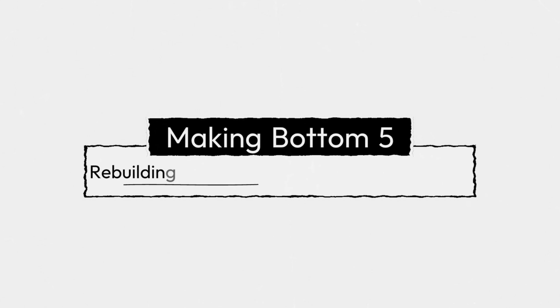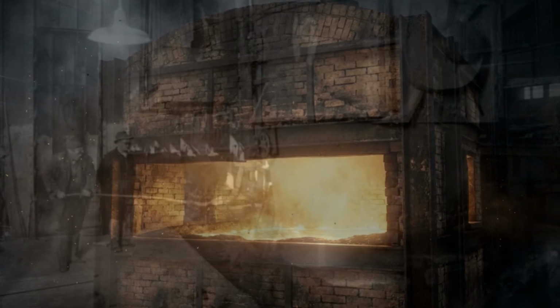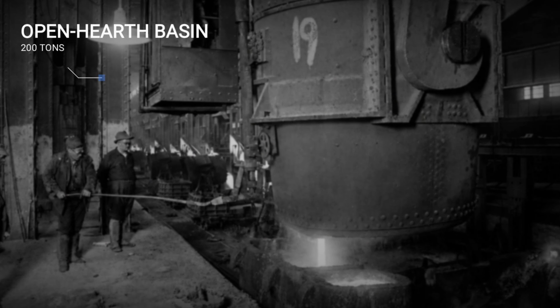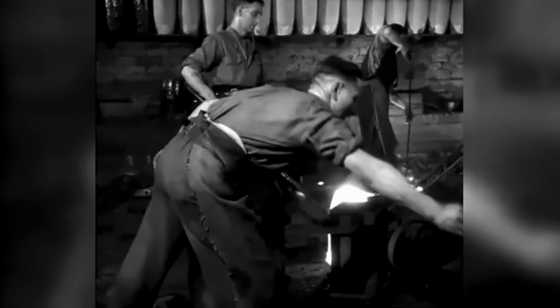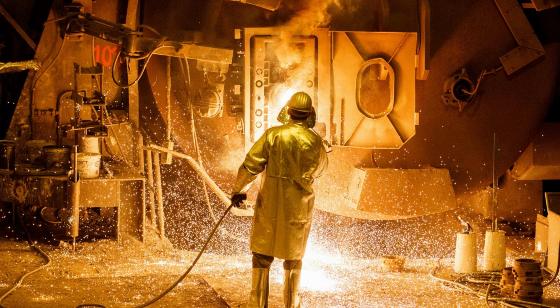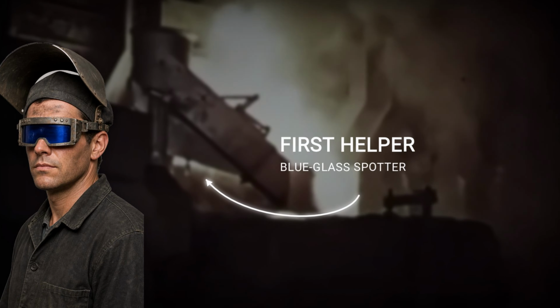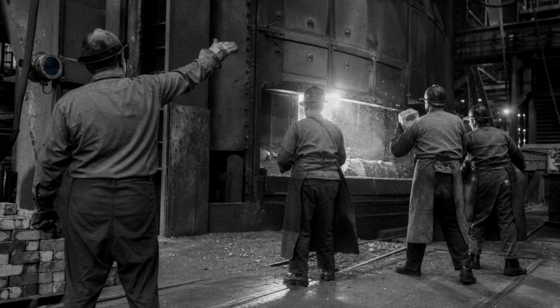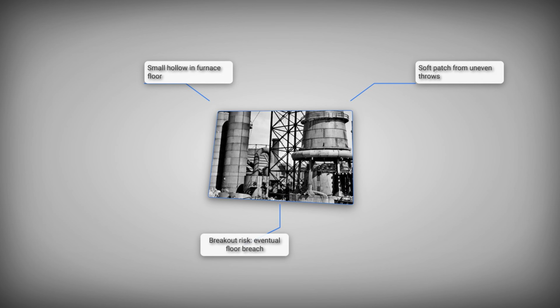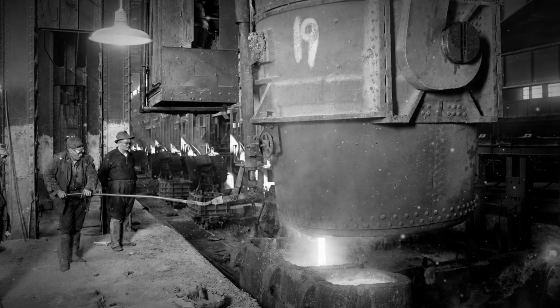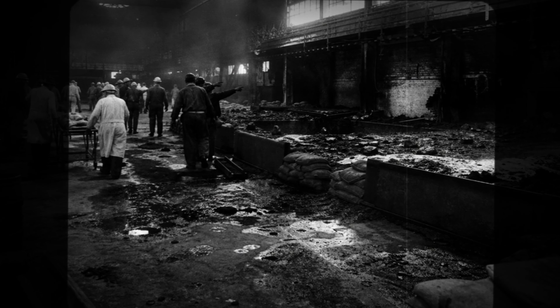Number 5. Making bottom. After every heat, the floor of an open hearth furnace, the basin that held 200 tons of liquid steel, needed repair, and repairing it was a craft with no written manual anywhere on Earth. The crew threw shovel loads of dolomite and magnesite into a furnace still glowing at welding heat, aiming through the doors at low spots 20 feet away, and the material had to land exactly where the wear was, fritting onto the hot surface in even layers. A first helper read the bottom through blue glass, mapped every hollow in his memory, and directed the throws like an artillery spotter. Build the bottom wrong, a hollow here, a soft patch there, and steel found the weakness, drilled into it heat after heat, and one day cut through to the ground in a breakout that could kill the furnace and the men serving it.